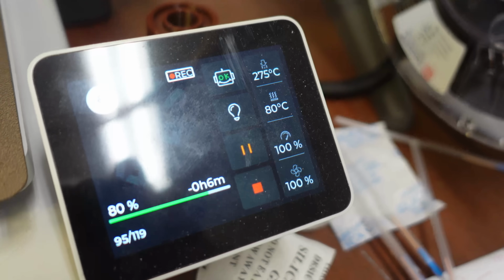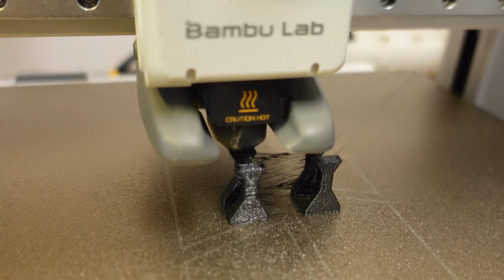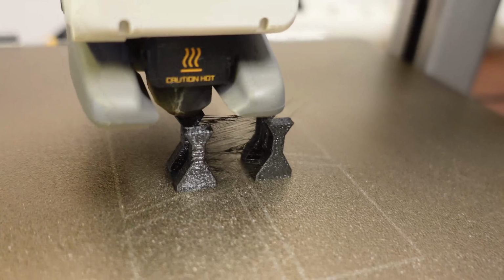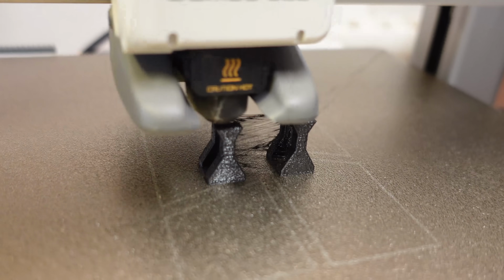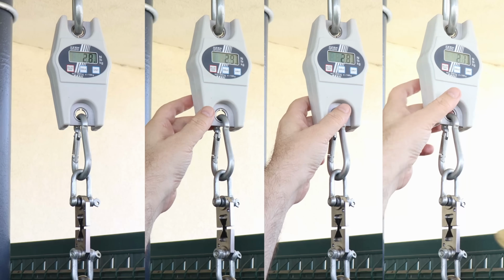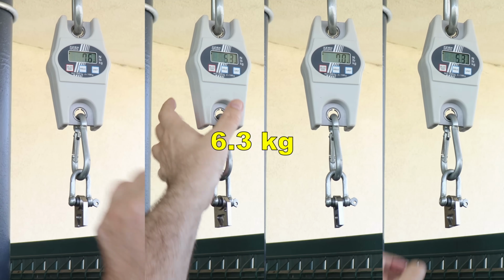Small gift for those who are still watching the video. So I tried with PETG on 275 degrees Celsius, and the result is quite a lot of stringing, so even if you try this, definitely it should be very dry. But let's see the layer adhesion. I have 4 test objects and you can see, very disappointing. Not really what I expected. Looks like some PETG materials, or maybe this graphene, start to degrade on these temperatures above 270-275 degrees Celsius. So the conclusion: don't go too much higher above the recommended print temperatures given by the manufacturer.